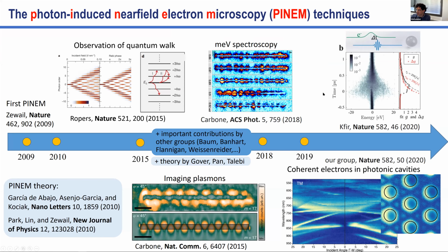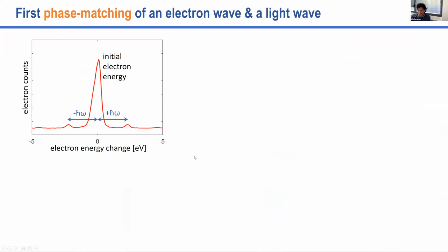And of course, I can give a longer talk on this. I just want to summarize and say that for us, the frontier now is to push the interaction to be as strong as possible. And for this, we're looking into an electron energy distribution like EELS. And in a regular interaction, what we see, this is the EELS picture now, is that the electron not only loses energy, but also has the ability to absorb energy. That's why the EELS here is symmetric on both sides.